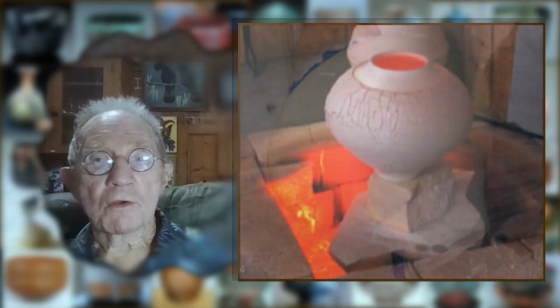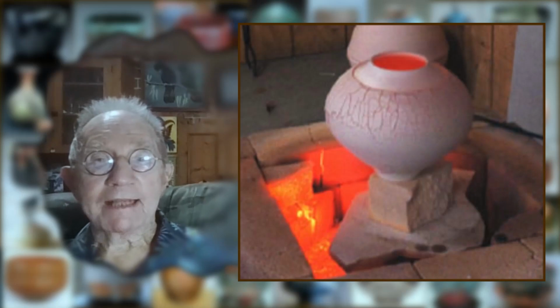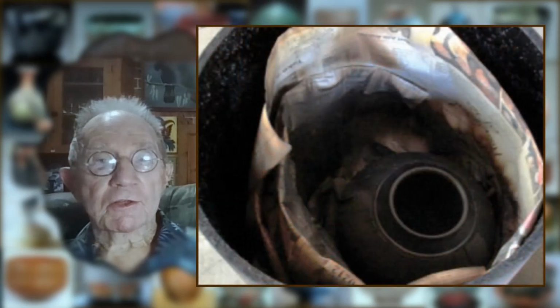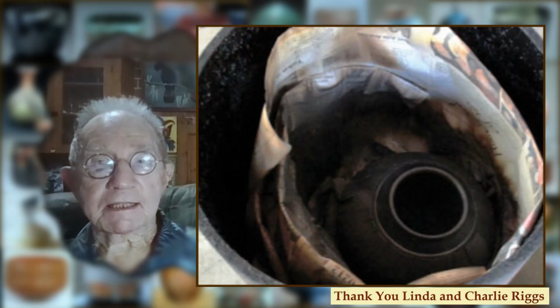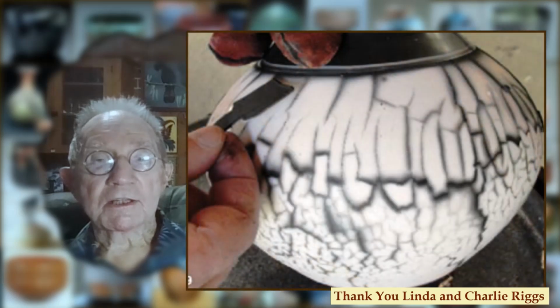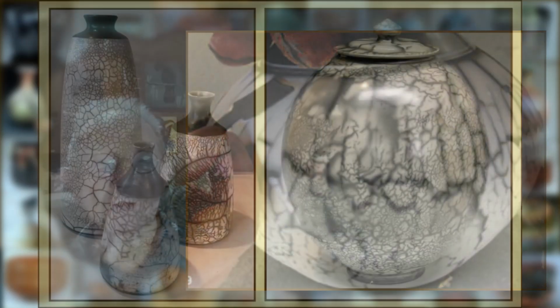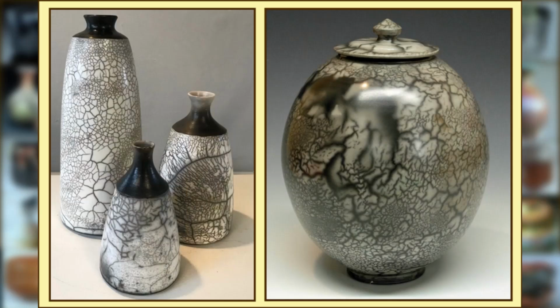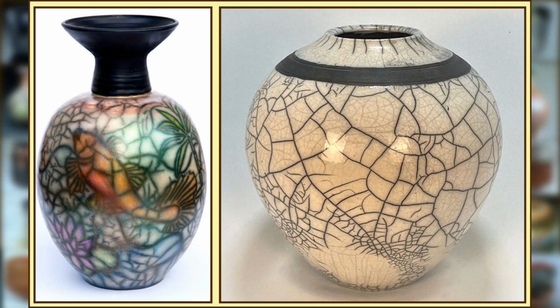The pot is removed from the very hot kiln and placed in the container with combustible material, and the smoke penetrates through the cracks in the slip to reach the surface of the pot underneath. The slip flakes off after the smoking to reveal a huge variety of very interesting black decorations on the surface of the pot. Sometimes the pots are coloured in various ways prior to this process to give extremely pleasant results.